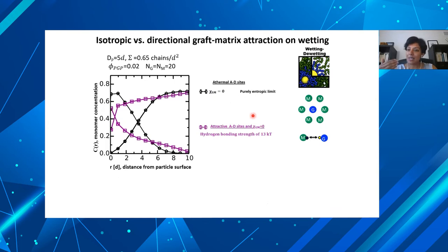And so let's now get into the science. We want to know what happens for isotropic versus directional in terms of wetting. So here I'm showing you a profile which is called monomer concentration profiles. As we go away from the surface of the particle, how do the graft monomers arrange? How do the matrix monomers arrange? You see the graft has a certain profile, dense near the surface. As the volume of the shell increases, you are dividing by a bigger number, so small values of the concentration. Matrix is penetrating the grafted layer. You can see that there's overlap. That was at the purely entropic limit, black line.